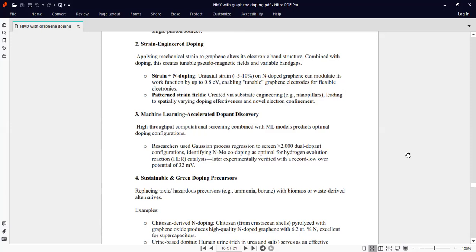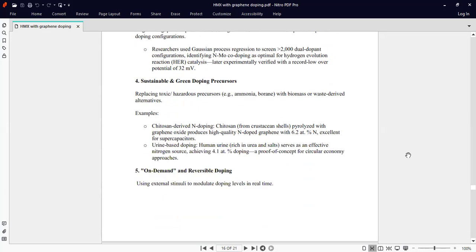Machine learning accelerated dopant discovery. High throughput computational screening combined with ML models predicts optimal doping configurations. Research using Gaussian process regression screened 2000 dual dopant configurations, identifying nitrogen-molybdenum co-doping as optimal for hydrogen evolution reaction (HER) catalysis, later experimentally verified with a record low overpotential of 32 mV.